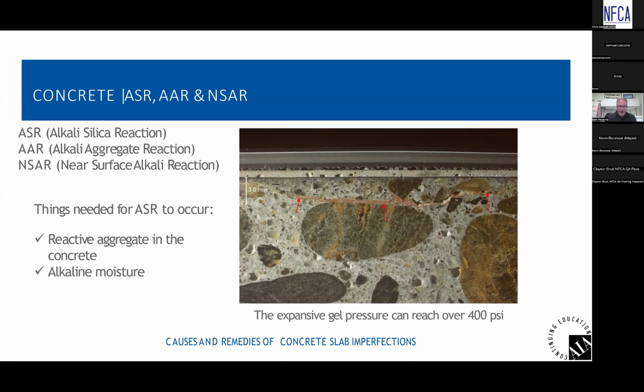So if we do have reactive aggregates, if we do have liquid water and alkaline water, a reaction can happen with this alkaline water and the aggregate that creates an expansive gel that can also reach PSI over 400 pounds. And that force can cause a pop out in the concrete. If there's no floor covering on the concrete, then there's typically never an issue because any water that's in the concrete just evaporates right out into the air and it never has a chance to react with the aggregate. But as soon as you put something over the concrete, then that water accumulates, you know, right at the aggregate. And if it's alkaline water at the aggregate, that's when the reaction happens.